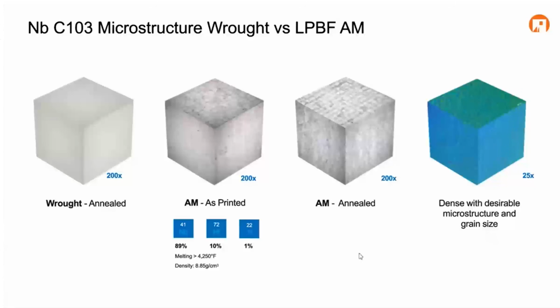And this is another material where, because of the unique microstructure and secondary phase formation from the laser powder bed fusion process, we see some real clear benefits for printing this alloy. So you can see here on the left-hand side, kind of the traditional wrought and annealed structure, typical cellular type grain morphology, and then when we look at the printed version, we can see very clearly in the as-printed as well as annealed that we still retain all of this weld macrostructure, which we'll get into why that's important here in a little bit.